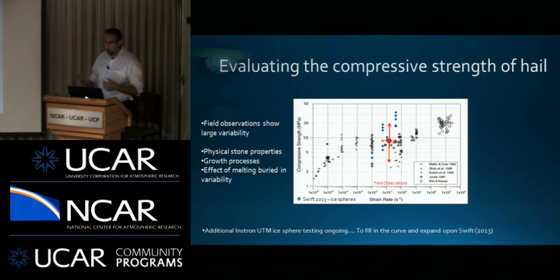But overall, what it would tell you, if you're going to do a material test based on an ice ball, is probably a reasonable assumption to use that's representative of just an average state. So if you were looking at revising material test standards, that may be a reasonable way to get away from that steel ball. So you can even go as far as, how do the physical stone properties matter, the growth processes, the dry and wet growth, which produces the layering structure, how does that play in?